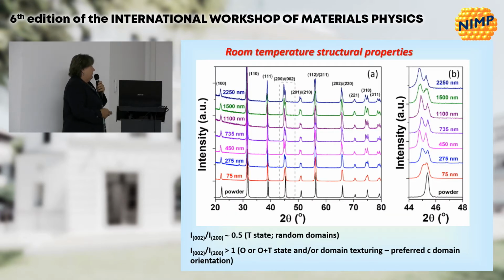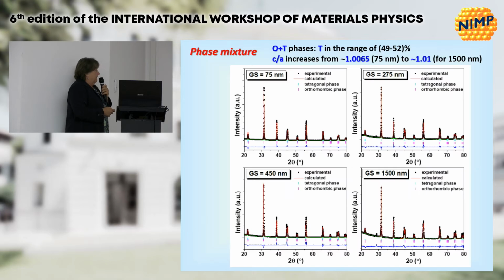Again, here are only the dense ones that I would like to report. The structural study with state-of-the-art XRD shows that for large grain sizes we have a tendency towards the orthorhombic state, while for small ones we have a multiphase state. For the fine ones, this peak is higher, it is not pure tetragonal, because the ratio of this peak should be half, but here we have a tendency towards tetragonal, and we started from pseudo-cubic powder. The Rietveld analysis indicated a phase superposition of mainly orthorhombic and tetragonal phases, half and half in this range, with a tendency, as I said, to the orthorhombic state for large grain size and tetragonal for small grain sizes.